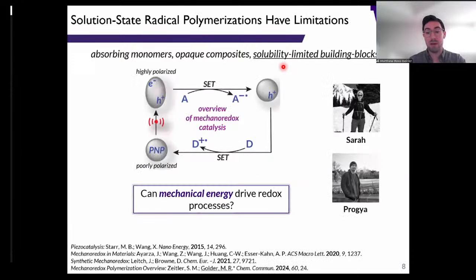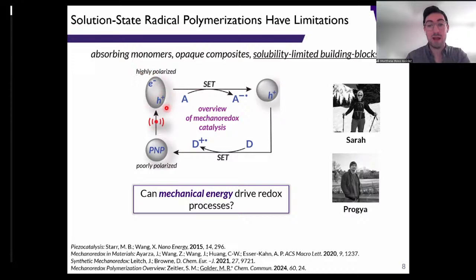And where we really think that mechanical energy or mechanochemistry can start to solve some of these problems. So the concept that we're after here, mechanoredox catalysis, invokes these metal oxide nanoparticles that are piezoelectric in nature. So you can take these metal oxide nanoparticles and exert an exogenous mechanical force or stress. You end up with this highly polarized state that is capable of undergoing single electron transfer to some type of acceptor, and then we can close the catalytic cycle through back electron donation to fill that hole.